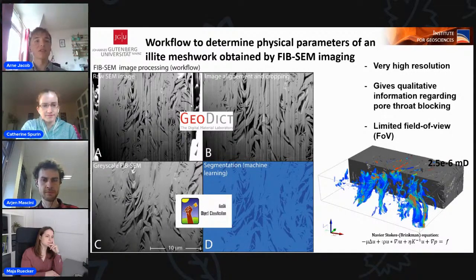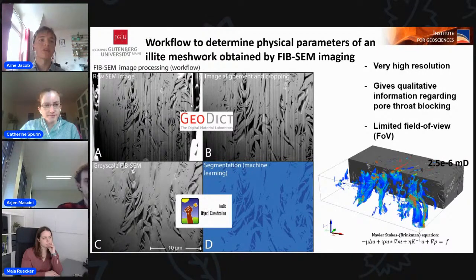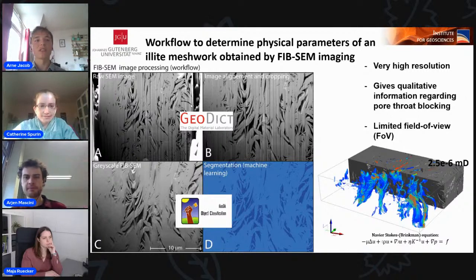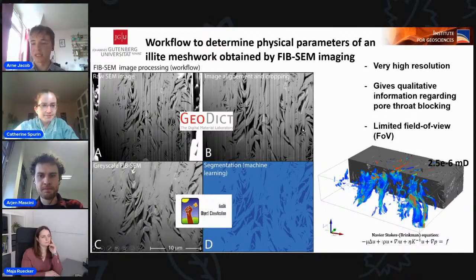Examples of the correct class or phase, in our case provided by the user, build a decision surface in feature space. Based on these features, a random forest classifier assigns each of the pixels or voxels to a certain phase. This method works for both 2D and 3D. We were able to obtain a very accurate representation of this illite meshwork using this workflow. Based on this segmentation, we calculated the permeability by applying the Navier-Stokes equation to the illite meshwork, as well as we did it with the synchrotron dataset.